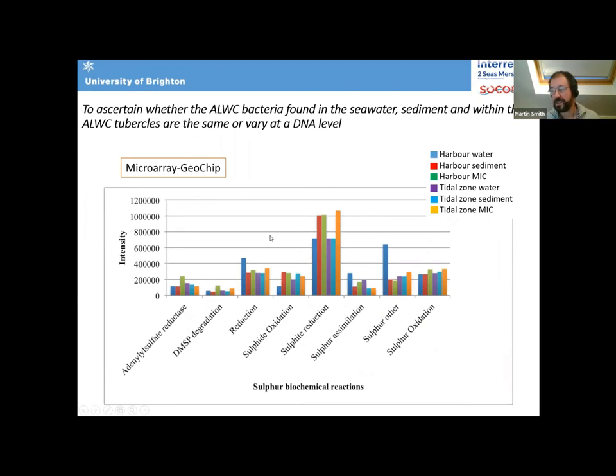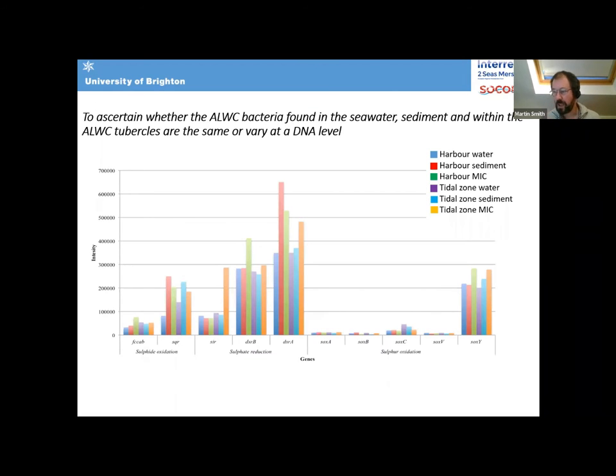So the first thing to look at here is the fact that in terms of sulfur biogeochemical cycling, we have genes operating throughout these sample types. And here we've got samples from microbially influenced corrosion, water samples, sediment samples. We have sulfate reduction going on, but we've also got sulfide oxidation. We've got different parts of the sulfur cycle, all as active genes within the microbial populations within those corrosion samples. So we can identify the individual genes that are active, particularly dsrAB, responsible for sulfate reduction, but then genes that are responsible for sulfur oxidation.